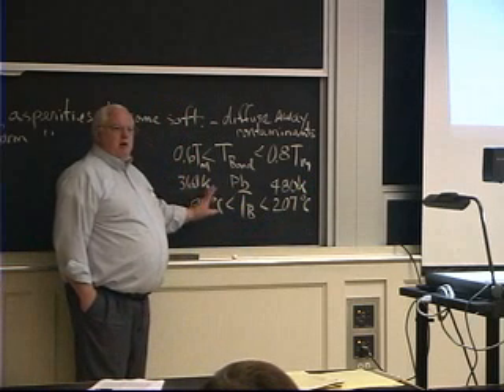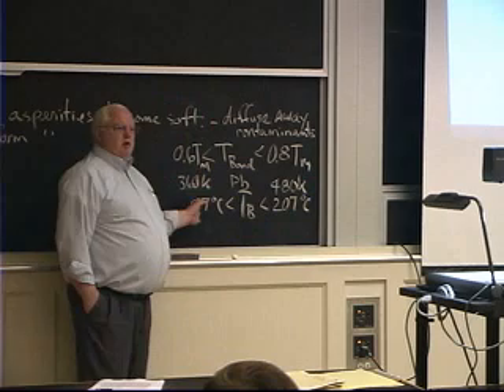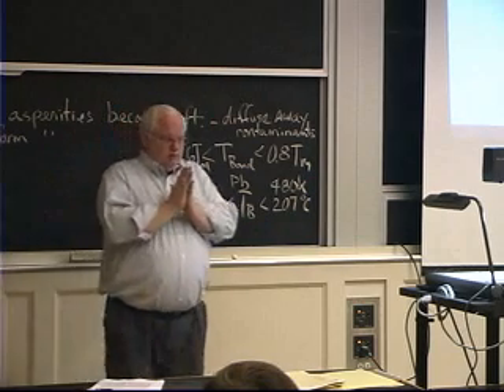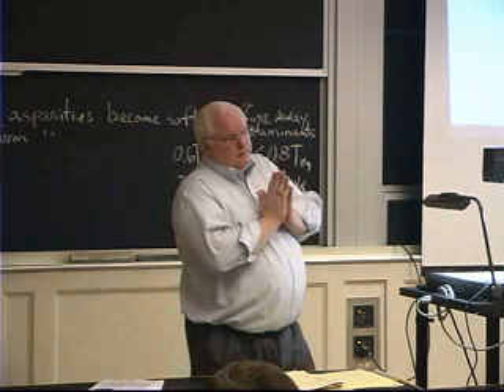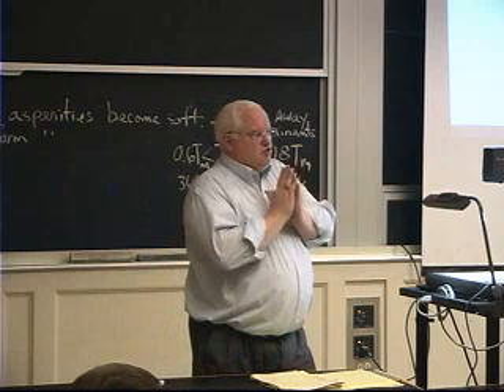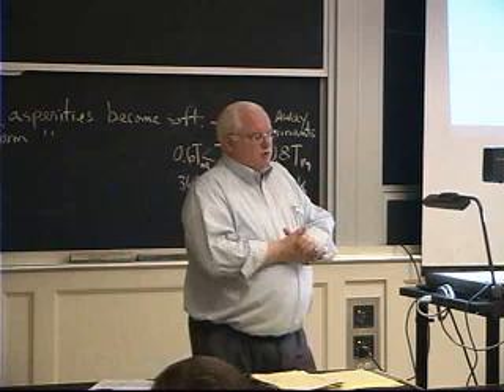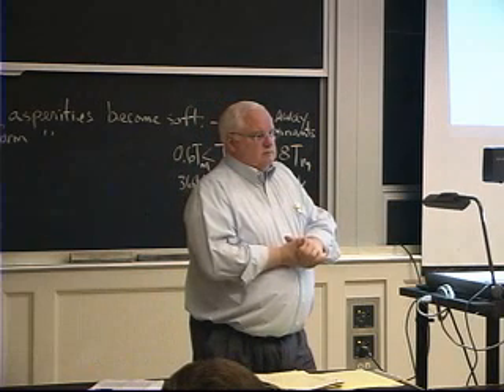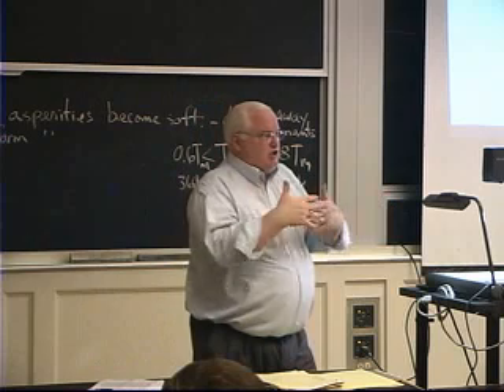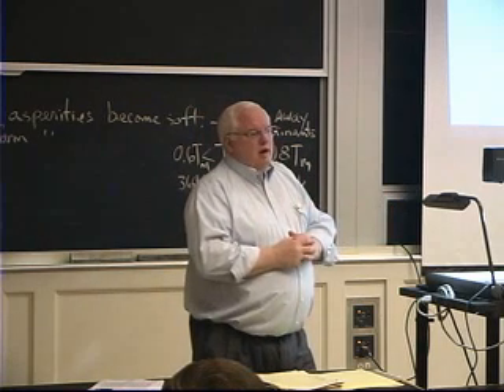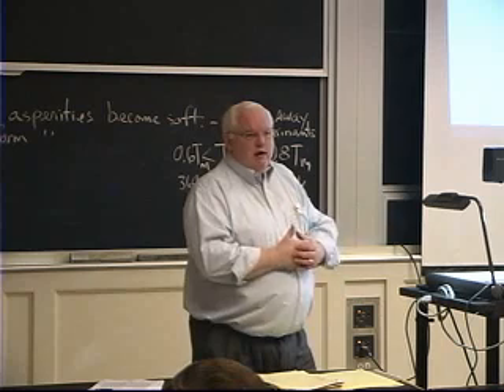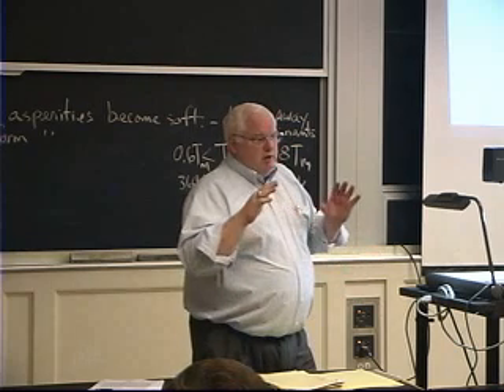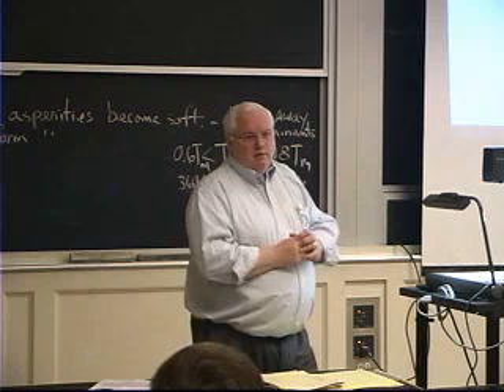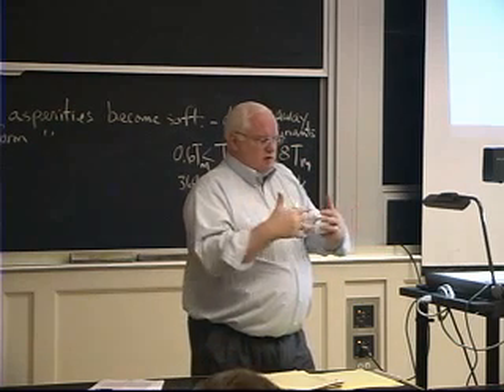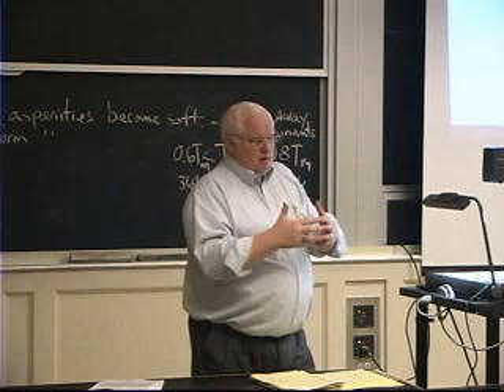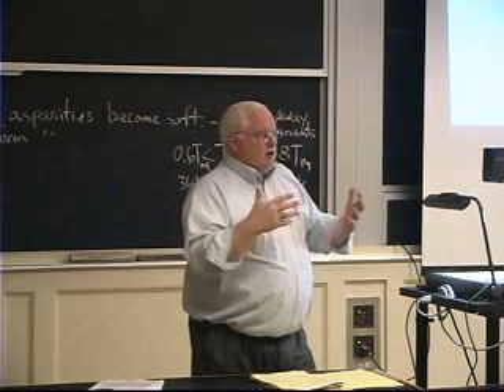One of the reasons that, well, anybody can think of a reason why it typically won't work at lower temperatures. Even if I had perfectly clean surfaces of lead, if I stuck them together at room temperature, why wouldn't I get diffusion bonding if I held them there for 24 hours? Turns out the diffusion is too slow. I mean, the atoms actually have to move and integrate themselves with one another. And if you look at the diffusivity of lead in lead at room temperature, it would probably take me 2 weeks. Okay, I could do it, and in fact, people have had situations where metals have bonded together under ideal conditions when they're slightly warm under long periods of time.